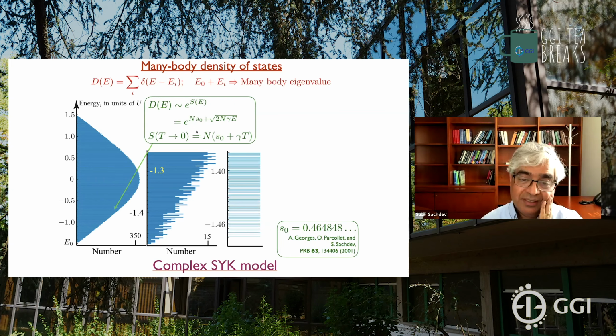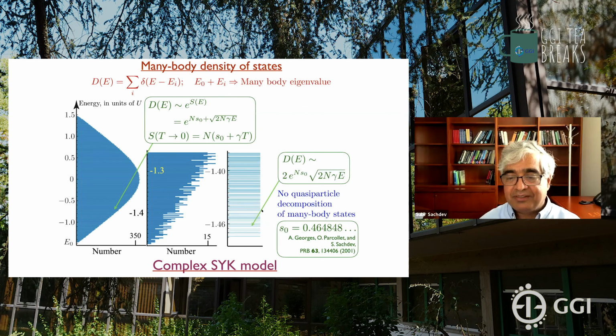There is no degeneracy. So here's the actual energy levels. There's no degeneracy at all, as you can see from my exact diagonalization of one set. But if you look at the density of states of this thing, now this has been computed, it's e to the n S0. So the key point is the following. In the middle of the band here, when the energy is extensive, the energy level spacing is e to the minus n. That's true in both problems I've shown you, the free particle problem and the interacting particle problem. However, at the bottom of the band, in the free particle problem, I had a very low density of states because I had a tail here.